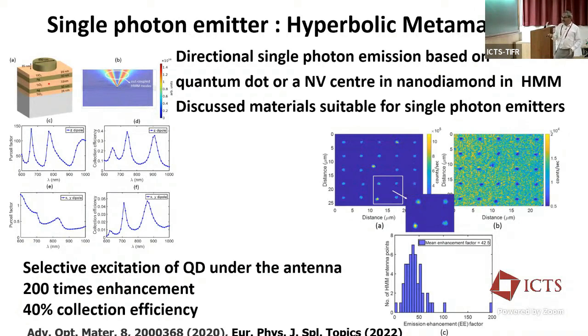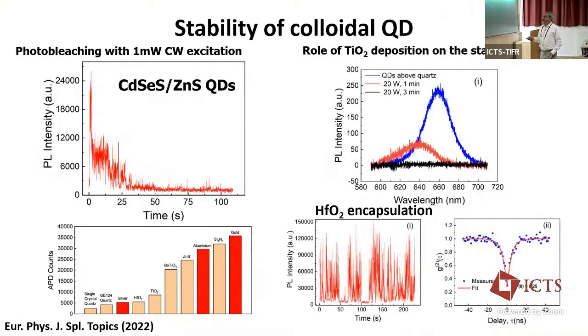So we have extended this to study which materials are more suitable to make these metamaterials from the point of view of stabilizing these nanodiamonds or quantum dots, so that the blinking and the photobleaching effects are not dominant. So we made these hafnium dioxide based structures, and we showed single photon emission from these devices in a directional fashion.